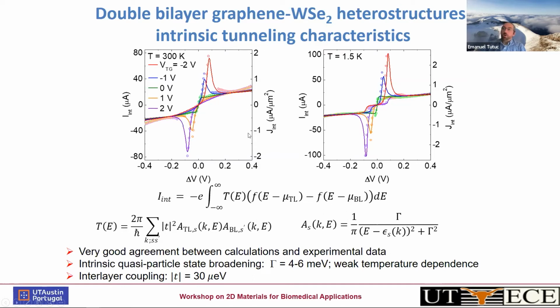One modeling parameter that comes out of this agreement is what's called the hopping energy of one electron going from one layer to another, and this really measures, if you want, the coupling from one layer to another. In this particular case, it's a relatively small number, 30 microelectron volts, but this is an example that we can have a functional heterostructure in a vertical direction, much like one would do with more conventional semiconductors.